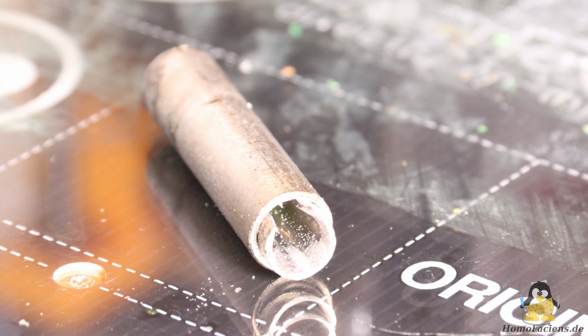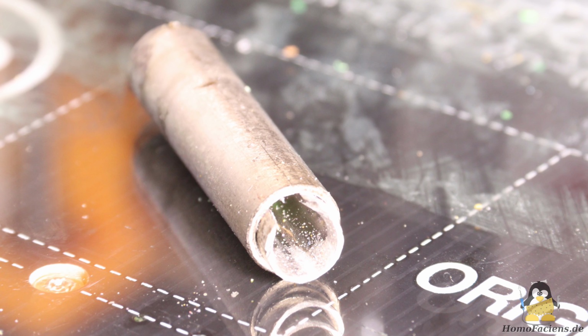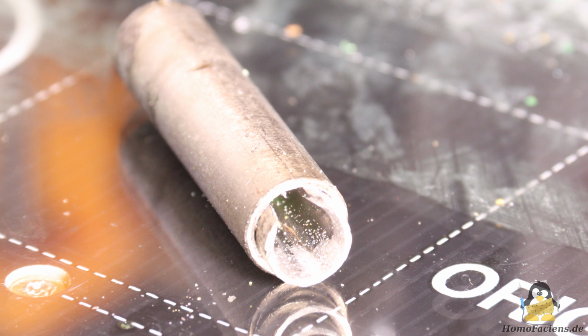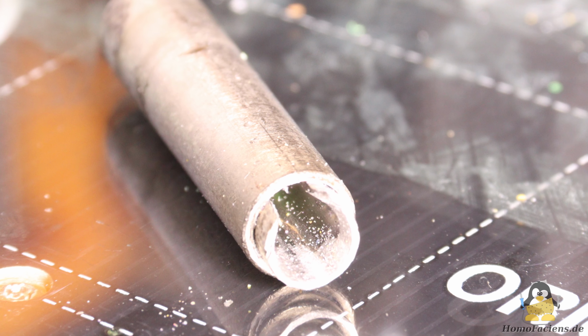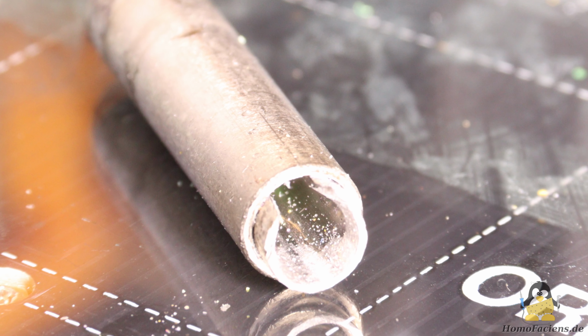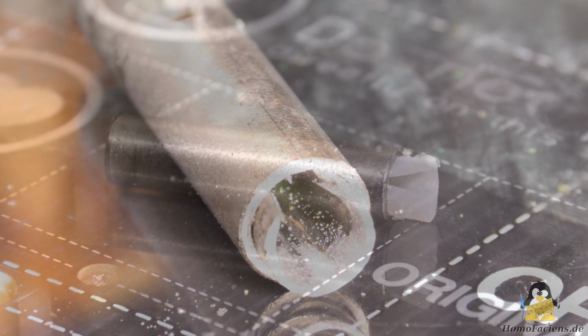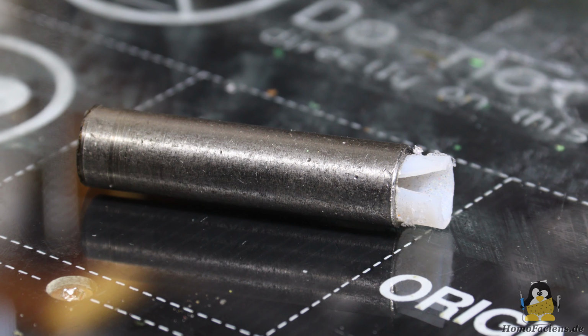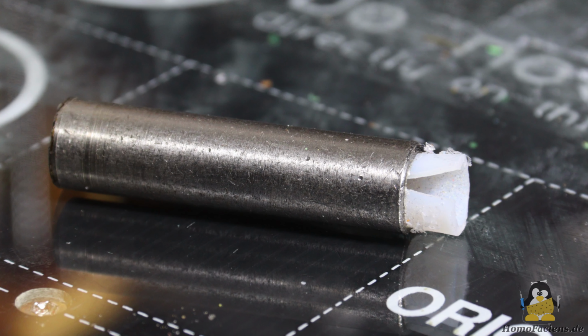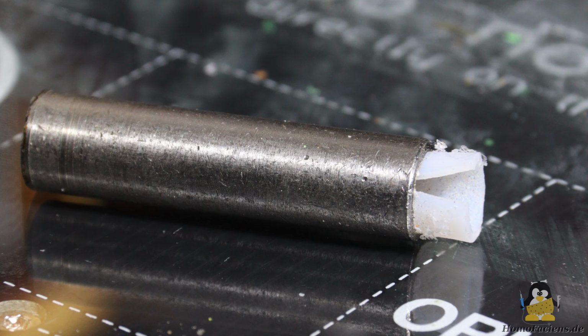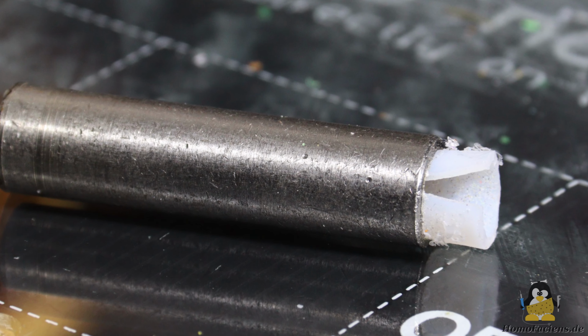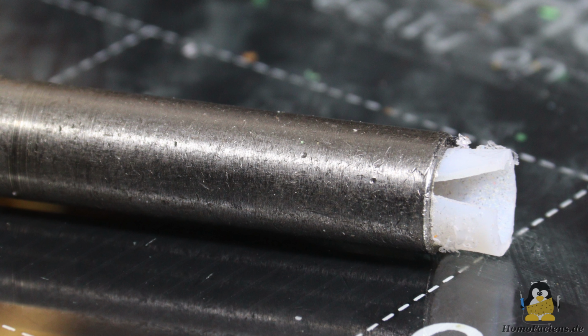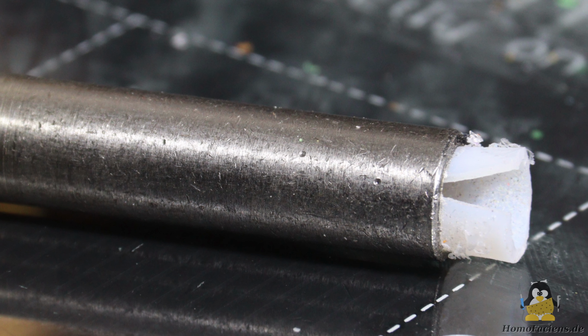So I polished a stainless steel tube on the inside, cut it open and inserted it into the extruder. But this version didn't really work well either. Teflon is a poor conductor of heat, and that makes another crucial difference. The plastic isn't heated by the extruder wall, so no film of liquid plastic forms here.